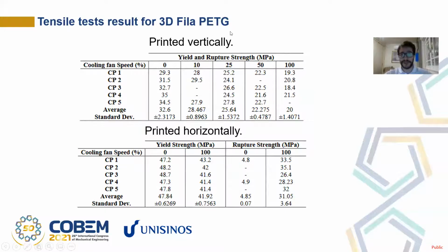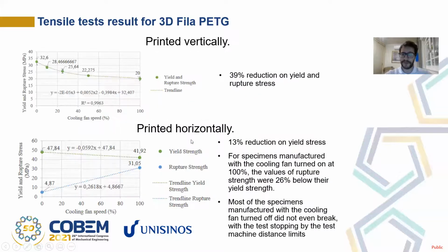And for PETG, we can see here for the ones printed vertically and horizontally that there is a different behavior. The difference in the yield and rupture stress points for the ones manufactured with the cooling fan off and on at the maximum was around a 39% reduction, with the cooling fan off being the most resistant one, and the other dropping a little bit more linearly here.